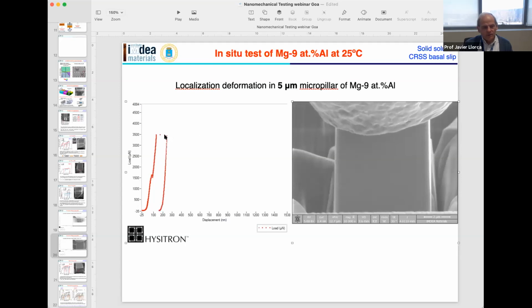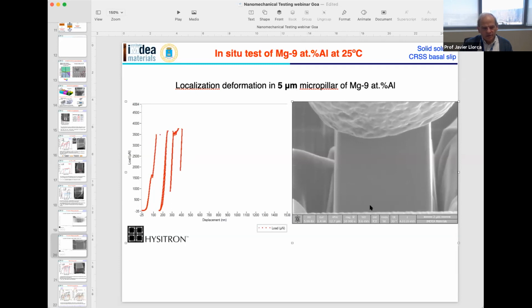You have here one pop-in. It's difficult to see. You will see the slip bands here later on. And then you increase, and you have another pop-in, increase again, and another pop-in, and more and more. Basically, you are activating different dislocation sources.